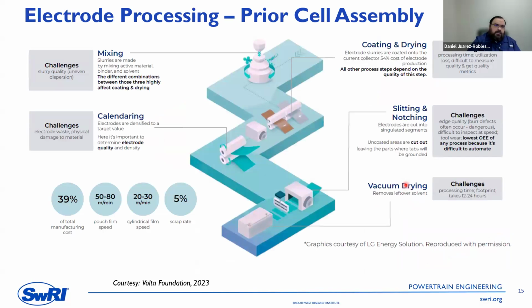Now, for the electrode within the cell, you still need to prepare the electrode. The electrode processing is also standardized. You need to have your powders that you need to put in the cell. You need to mix them. You need to have the dry mix, then the wet mix, when you introduce some solvent and some binder, and the binder will glue all the particles together. Then you will cast it onto the copper or aluminum foil, depending on which chemistry you have. Some of the new chemistries only require one of them. Once you cast it, you need to dry it. When you dry it, this powder will stick to the foils, and then you can start trimming or cutting the electrode to the right size and put it in the cell.